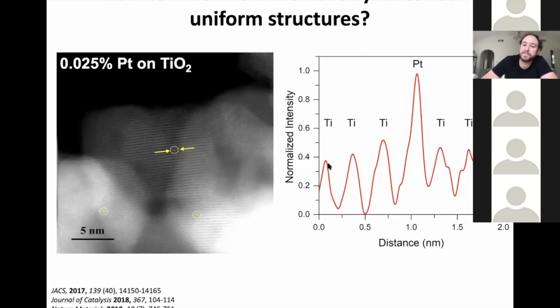So each one of these peaks here is me looking down a column of titanium atoms, and then all of a sudden we see a hop up here. And this is because platinum has an atomic number about 3 times higher than titanium, which means it scatters an electron beam with actually about 9 times higher intensity than titanium does. And so you should see a spike in scattering intensity in the electron beam that goes back down when you get to the next row, to identify that you have these single atoms. So this is the best approach to being able to characterize things by electron microscopy.